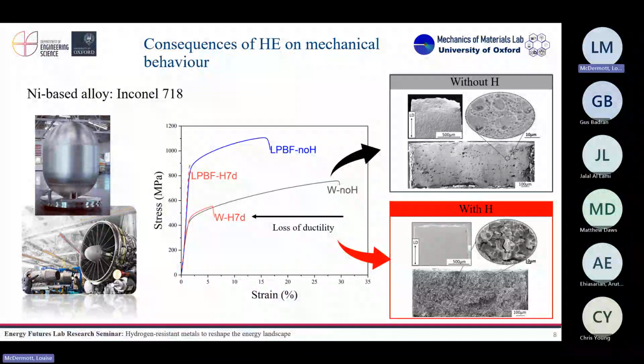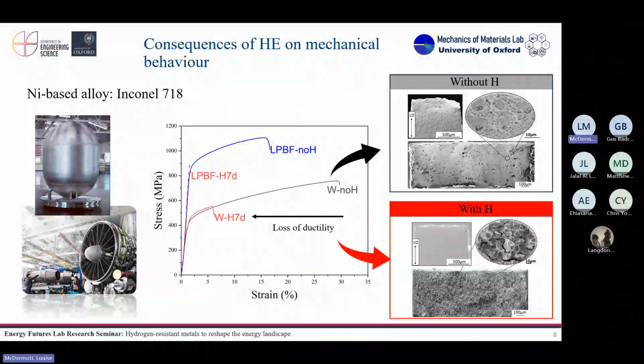And what happens when we have hydrogen in the metal is, if this is our standard stress-strain response, what hydrogen does, the red curve here, is, as the name says, cause a great loss of ductility in your material. And this translates into a very brittle behavior. You can compare here two samples that were tested without hydrogen and with hydrogen. In the upper one, you can see ductile behavior, with some reduction in area of your sample before fracture, while in the hydrogen one, the fracture is completely brittle, and you can actually see the intergranular fracture that's typical of failures due to hydrogen embrittlement. So this is what hydrogen does to your material.